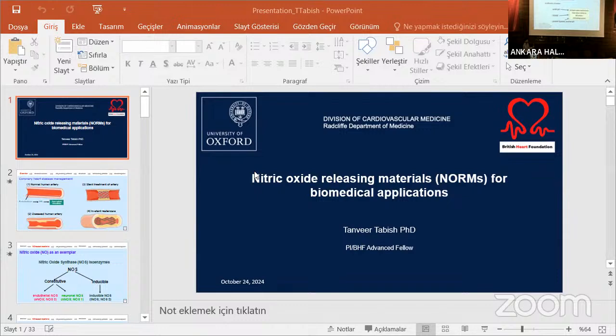So that's also delivered to the body. We got this idea from this acidification of nitrite, and we conjugated this to porous graphene oxide. First we made porous graphene oxide, then we conjugated cysteamine. Cysteamine has amine and thiol groups, so that's conjugated, and then we conjugated nitrite, in acidic conditions, and now we call it S-nitroso cysteamine functionalized graphene.